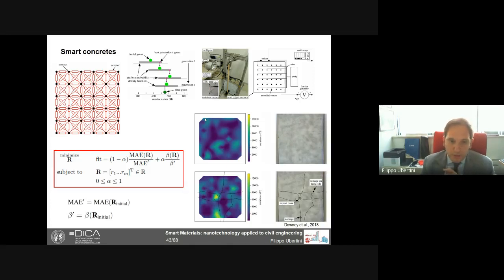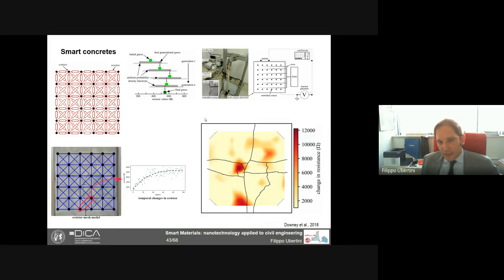We fit the inverse problem, and we get the map that you see in the bottom. And you clearly see the yellow spots in the middle and in the middle at the bottom, where we have the most prominent damages. We have some detachment of the material there. So maybe we do not really follow the cracks, but for sure we follow where we have some detachment of the material. If we take the difference between the map after damaging and before damaging, this is even more evident.